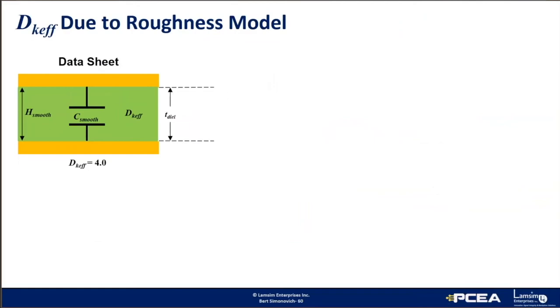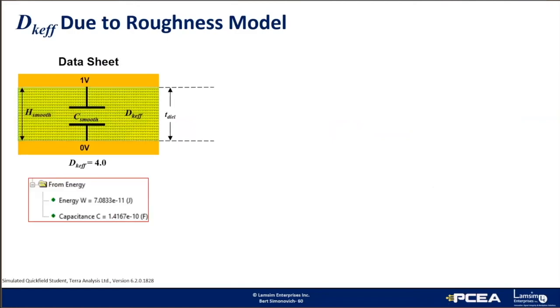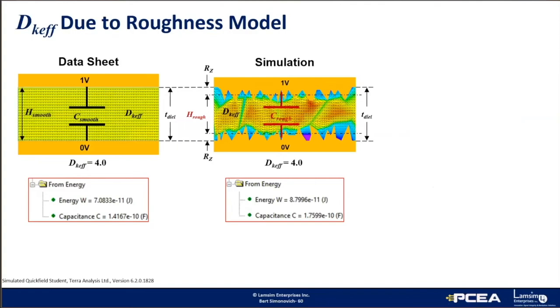This is further explained by the Dk effective roughness model I developed. Normally, Dk/Df tables publish effective Dk assuming the smooth foil of the fixture. If we model the structure with a Dk effective of 4, we see the uniform electric field lines. For this example, the capacitance with smooth copper is 141 pF. But in reality, the finished laminate sees the roughness tooth profile embedded into the cured dielectric. When we simulate the structure, we see the capacitance increases to 175 pF.